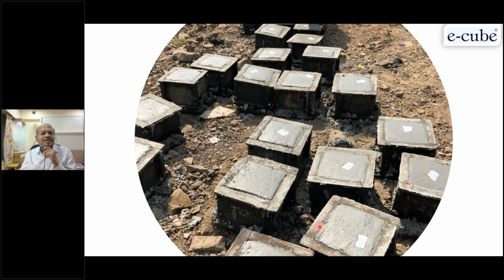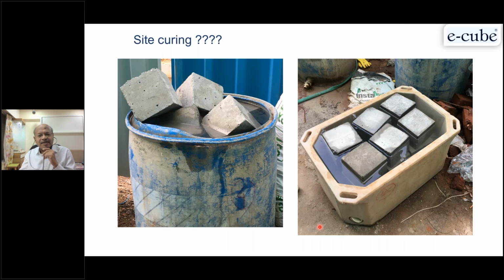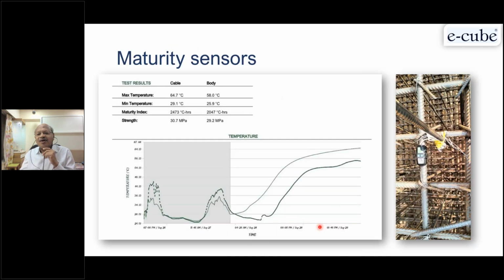Now these maturity sensors are also available today. We can insert them into the concrete and you can take real-time strength. This is one of the projects where we did this exercise, and this is the actual concrete. This is M35 concrete. We have used only 120 kg of cement and 280 of GGBS, and we are able to achieve strength of 29 MPa in 7 days.